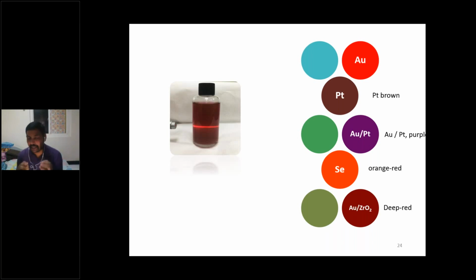And especially the selenium nanoparticle, we are working on extensively now. It is one of the cheapest materials compared to the gold nanoparticle, but it can give you high stability, high sensitivity, and a low detection limit. We have developed this kind of material. And one more, the deep red color can be given by gold with zirconium oxide. So these are the nanoparticles we have developed, and we have collaborated with some other companies who are manufacturing rapid test kits with low cost and high efficiency.